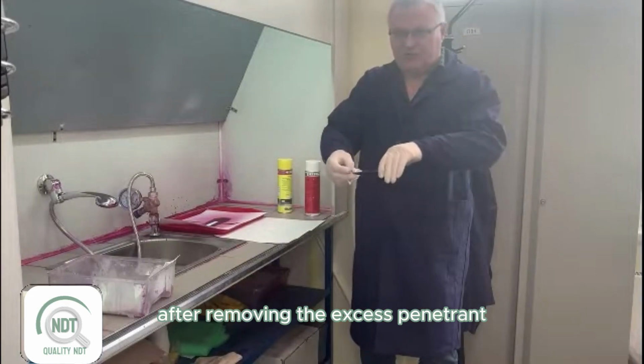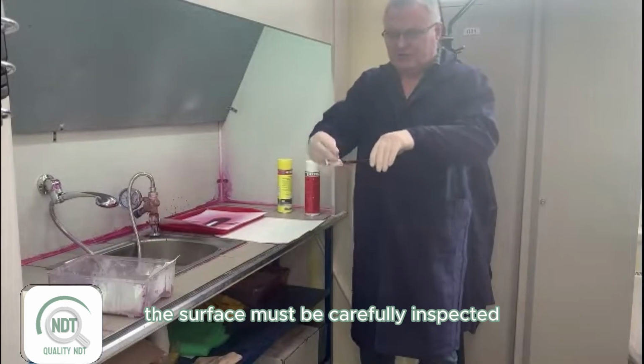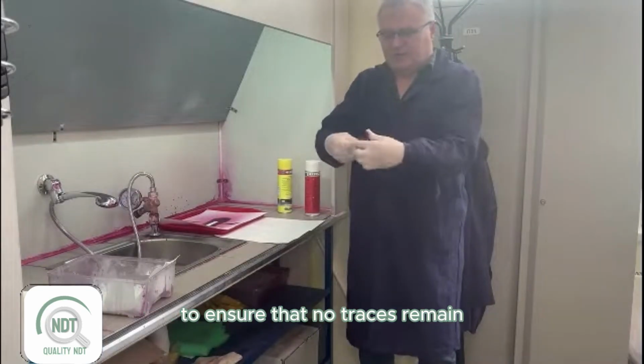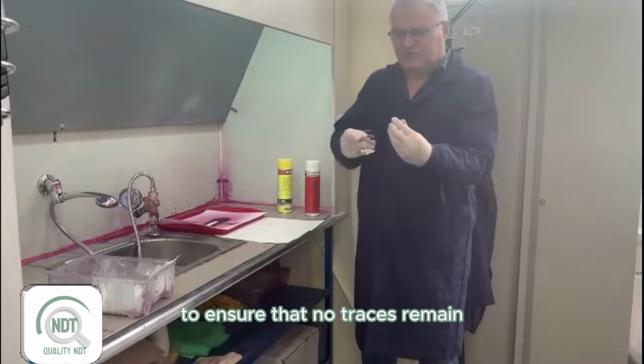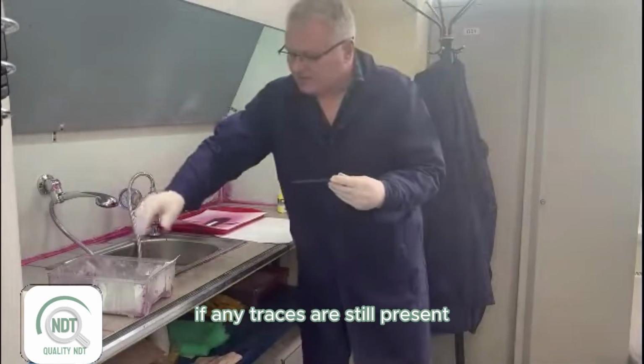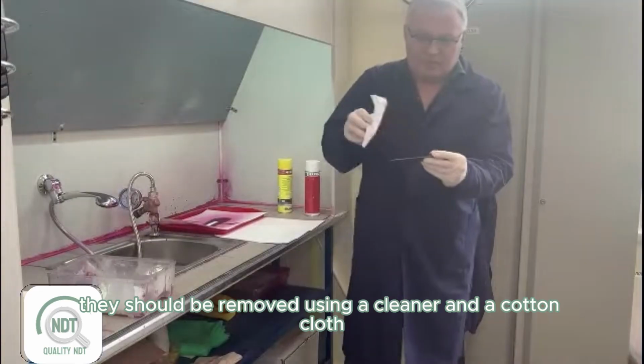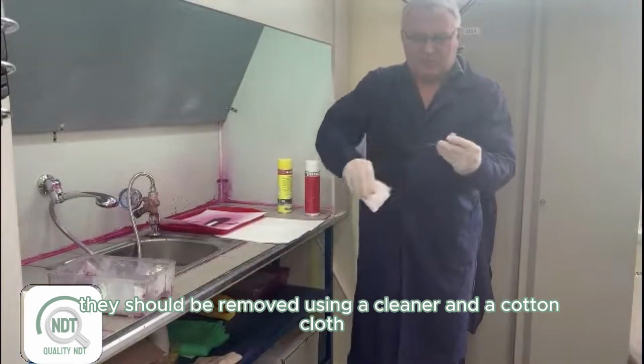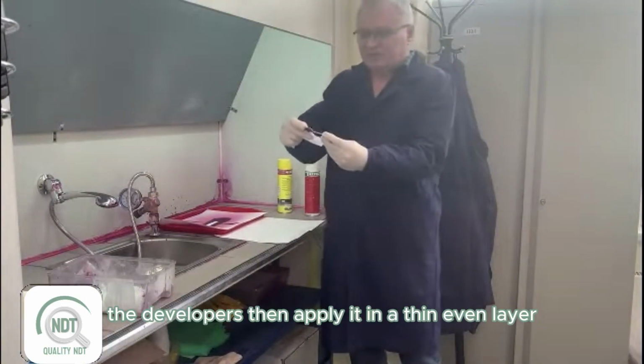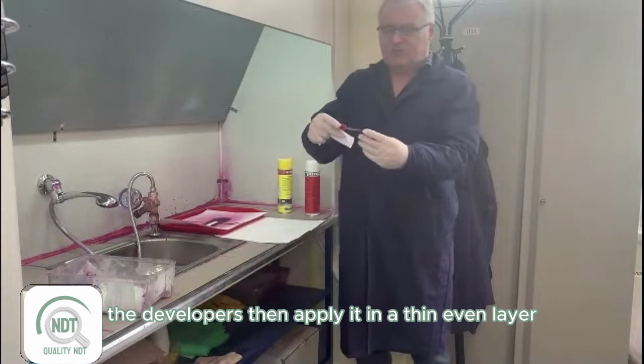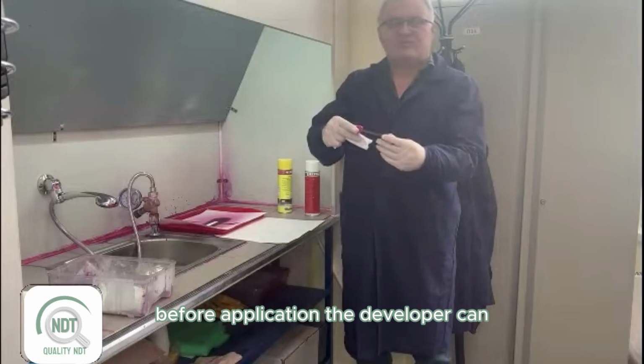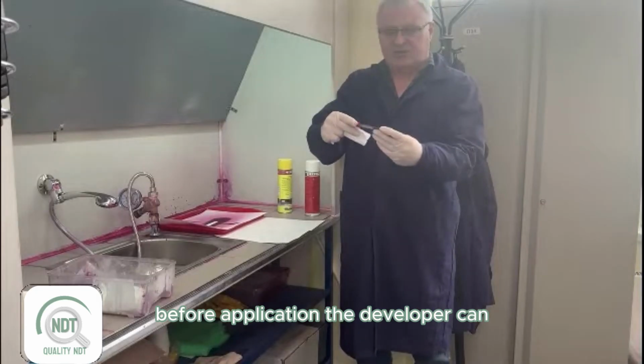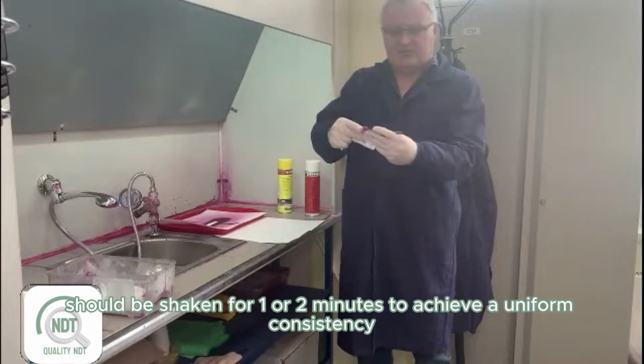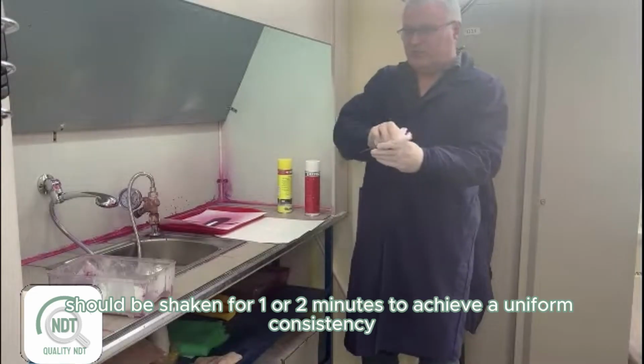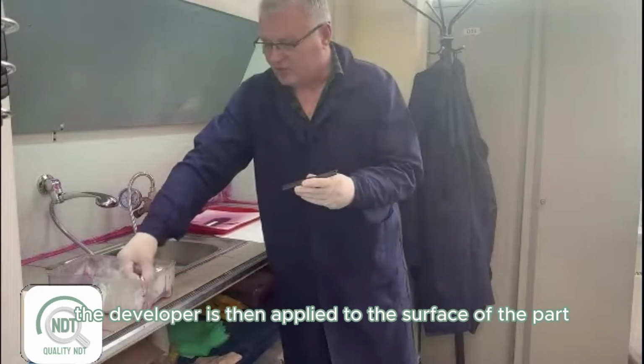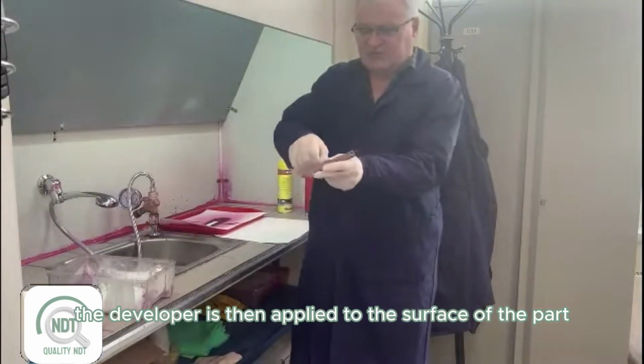After removing the excess penetrant, the surface must be carefully inspected to ensure that no traces remain. If any traces are still present, they should be removed using a cleaner and a cotton cloth. The developer is then applied in a thin, even layer. Before application, the developer should be shaken for 1 or 2 minutes to achieve a uniform consistency. The developer is then applied to the surface of the part.